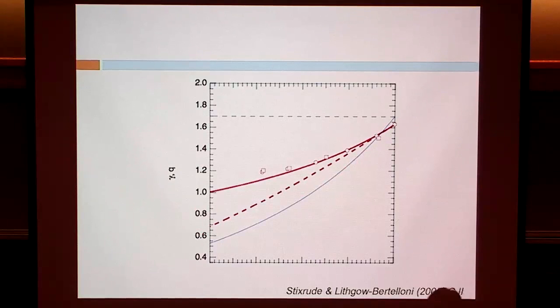Lars? Yes? So you've got Q dropping below 1 at low volume, so high pressure. So that means at very high pressures, you actually get increasing thermal pressure? Yeah, that's right. Which is interesting. That's what comes out of the ab initio theory. The limit at extreme compression is gamma goes to 2/3 and stays constant. So under those conditions, yes. That's right.